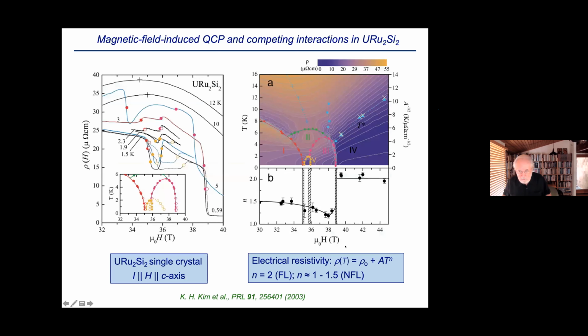All right, but anyway, this is relevant to what I want to tell you now, because this is work done. There are a number of papers reporting this, but I think the first one was in 2003. And these are high field measurements on uranium ruthenium-2 silicon-2. This is resistivity versus field at high fields in this range right here. And so basically they find these curves at, say, 12 and 10 Kelvin. But then as you lower the temperature, these curves develop some remarkable features. And then from these features, you can pick off certain temperatures and fields from which they could deduce a rather complex phase diagram in the vicinity of what appears to be a quantum critical point. I'll come back to that in a moment.